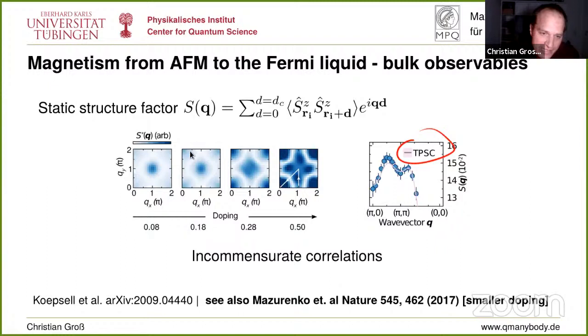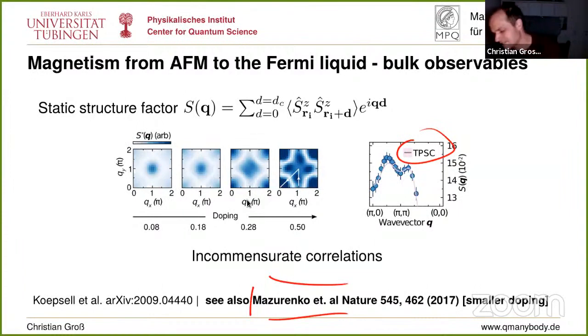And I should say, in that paper I was talking already about in Markus Greiner's group, where they actually implemented this entropy redistribution trick to get colder, and they got colder than we are. They also studied basically this static structure factor, but they stopped at rather low doping levels. So they somewhat stopped here. So they kind of see the smearing out signals, but they didn't measure to this incommensurate point that we see here. So our measurements build heavily on the ideas that were developed in Markus' group here.